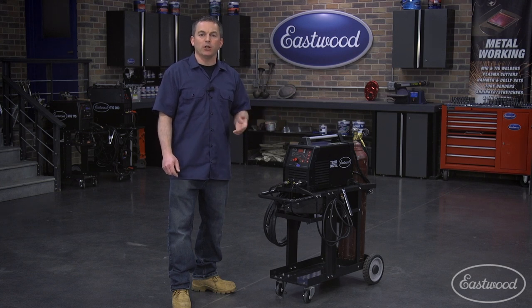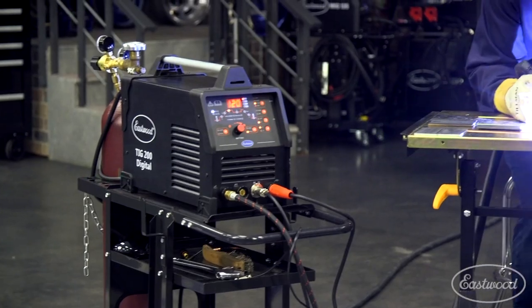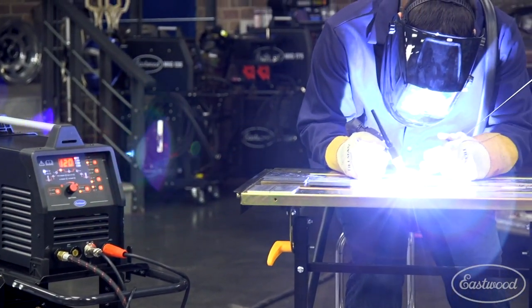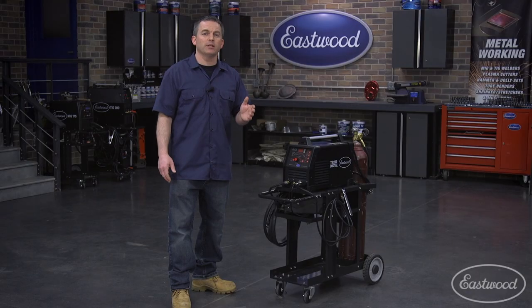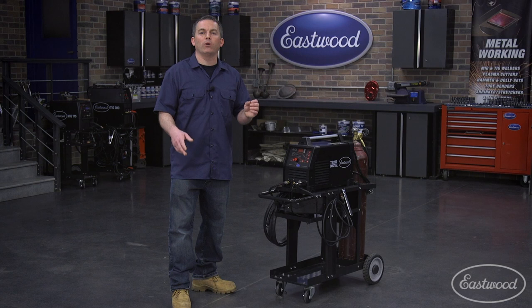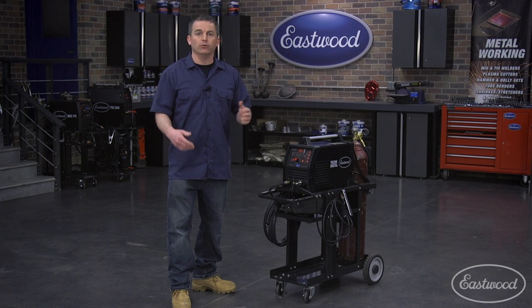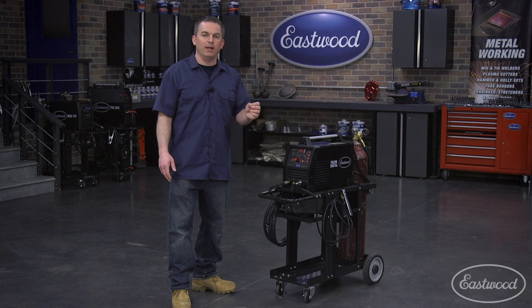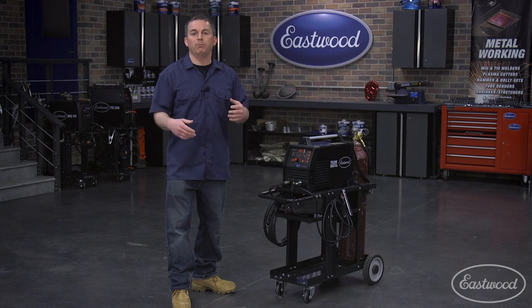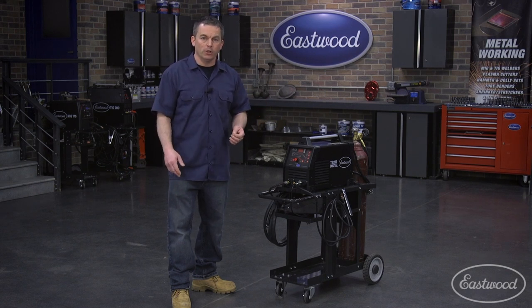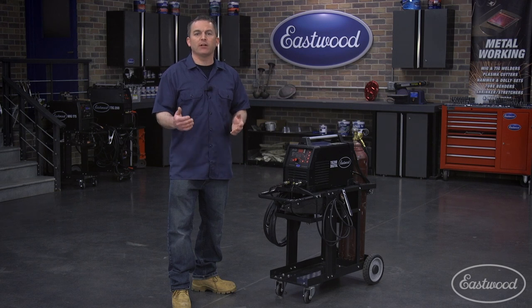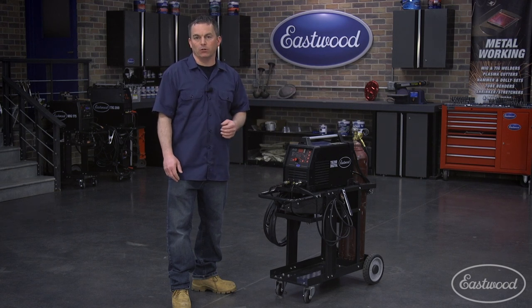By increasing the frequency, the current changes direction more often, which gives the arc cone less time to expand. This means that the arc is more focused at the precise spot the electrode is pointing. This is ideal when precise penetration is required because it allows you to weld very tight joints with good penetration without laying down too much filler material. Use high frequency in an inside corner joint or fillet weld so you can maintain a good weld bead in the corner. If the pieces you're welding have wider gaps or require more material to build up the weld, you'll want a larger arc cone, so you'll use a lower frequency. An outside corner joint would be an example of when you may want to use a lower frequency.